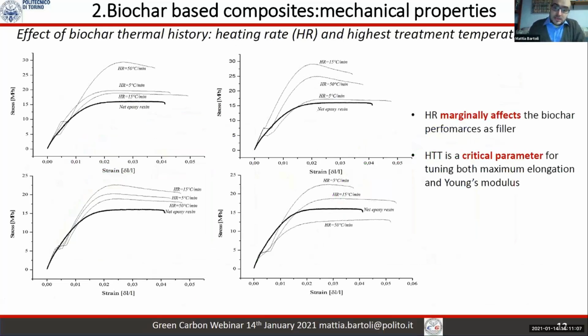Finally, we checked the effect of pyrolysis temperature and heating rate. Those are the main parameters that could be faced during biochar production, because they are very important for the whole pyrolytic process. And we found that heating rate is not so important, but the highest treatment temperature used for the production of biochar is a key parameter and could be used to shift from a brittle material to a ductile one.